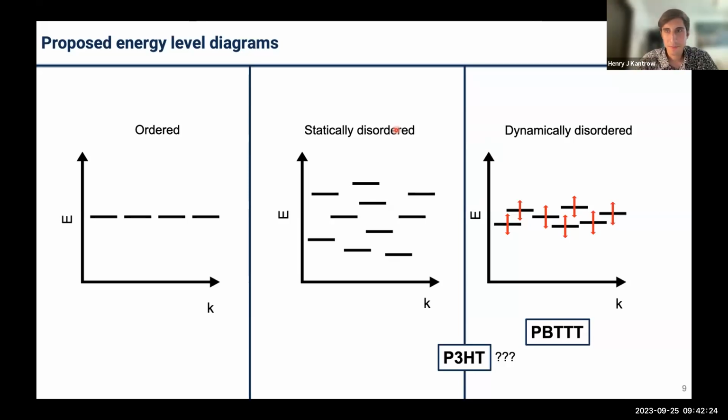Yeah, so maybe to give the brief answer, and we could talk more offline if you're interested too. This previous data that I showed you on P3HT, the original one from Felix, is using an implementation where you actually detect the signal incoherently, and you use lock-in detection to isolate the coherent part of your signal.